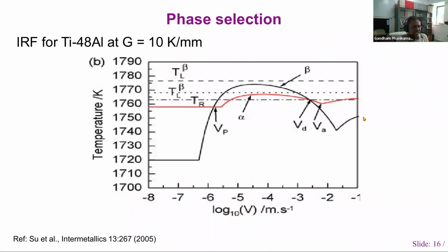Okay. Now here is a place where there's a competition between two different phases. The black curve is the interface response function for beta phase, and the red curve is the interface response function for alpha phase in a titanium aluminum alloy. And as I told you, the upper envelope gives you which phase will form. So which means that at lower velocities, alpha will form, at intermediate velocities, beta will form, and at very high velocities, again, alpha will form. Now that kind of information of phase selection is possible once we are able to model the interface response function.